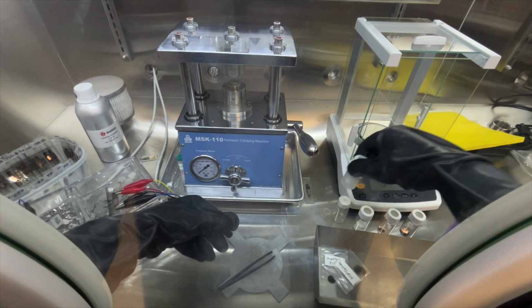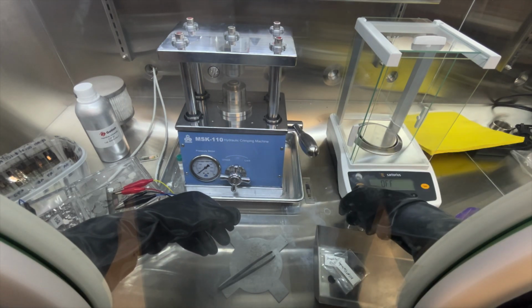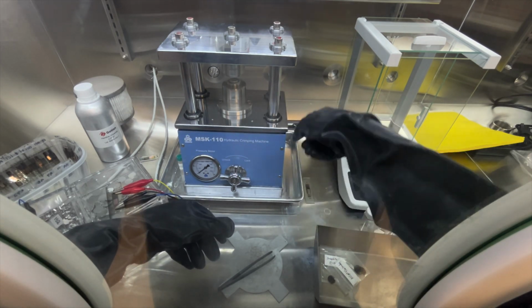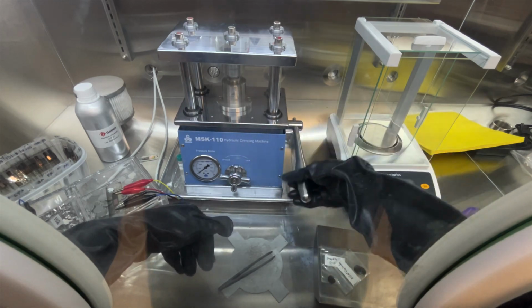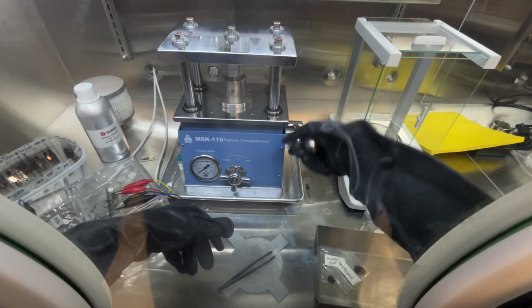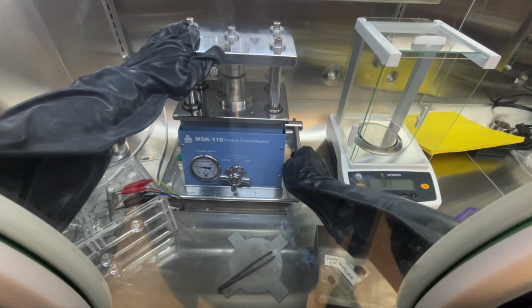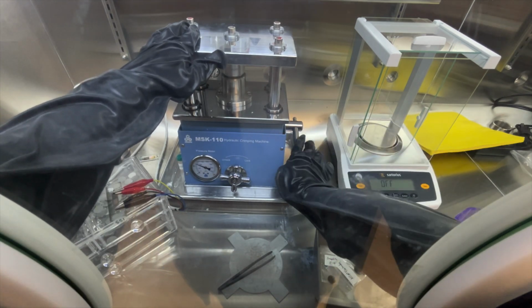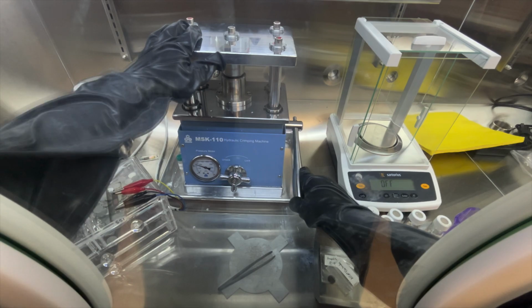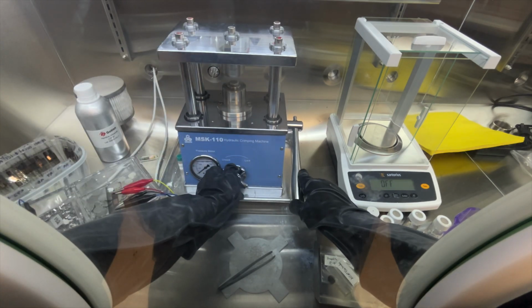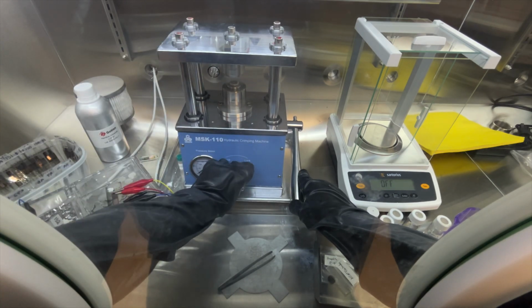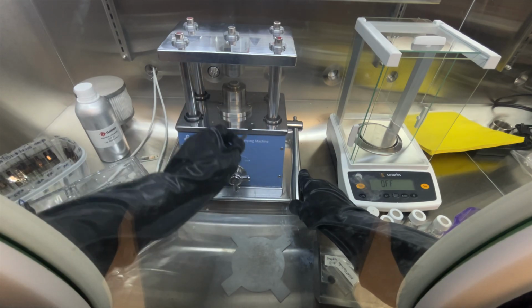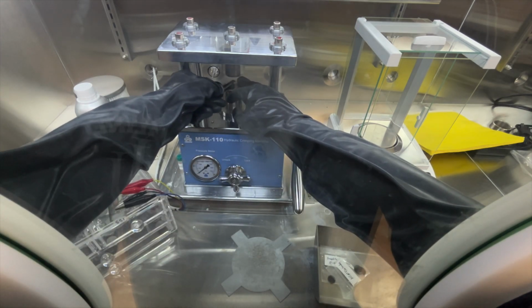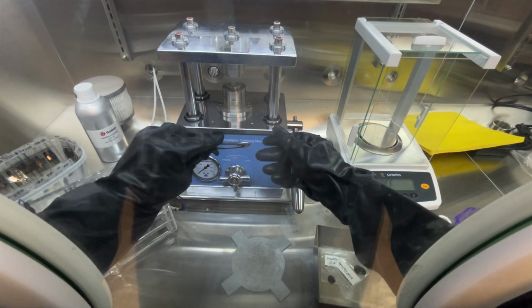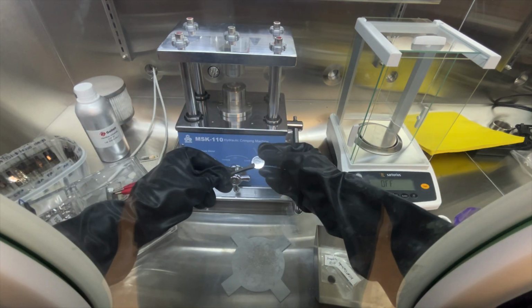Making sure the knob is turned to the lock position, I then place the device into the notch and begin raising the platform. I will do this until the pressure on the gauge reads between 800 to 1000 psi, and then I will wait 10 seconds before unlocking the knob. Before the next use, I'll typically return the knob to the locked position. Using the tweezers to remove the sealed device, it is now finished and ready to be plugged into the current boxes for testing.